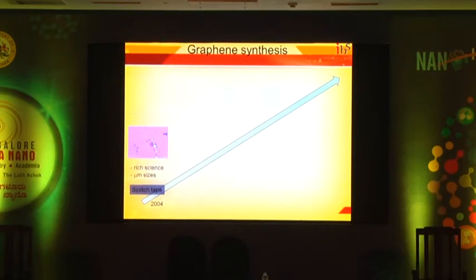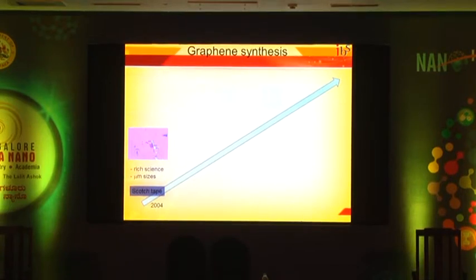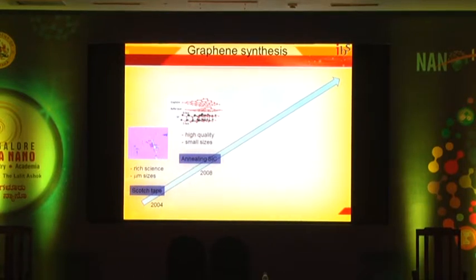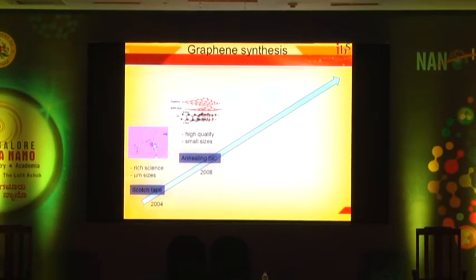So the first question: when people started with Scotch tape, which gives a small-size flake, of course industry people said, oh, this is useless, only good for scientists. So then people started thinking, how can we synthesize large areas? Of course, people started with silicon carbide, which is alternating silicon and carbon, and people simply tried to anneal at very high temperature, and you can see at the top of the surface, suddenly a graphene layer is formed. But silicon carbide is very expensive. People don't like that idea, and also it's not so easy. Still, from an industry point of view, this is not desirable.